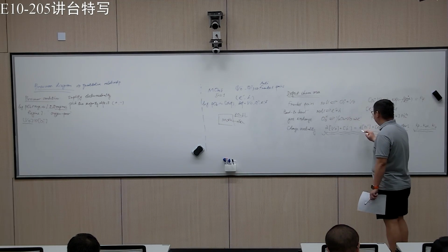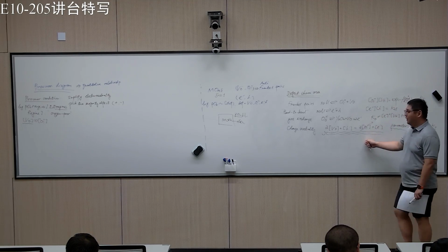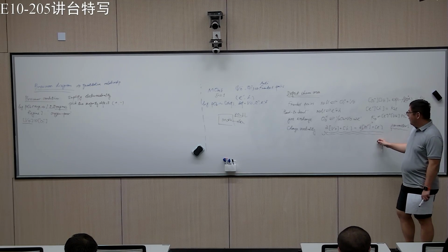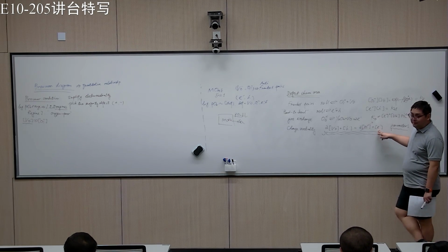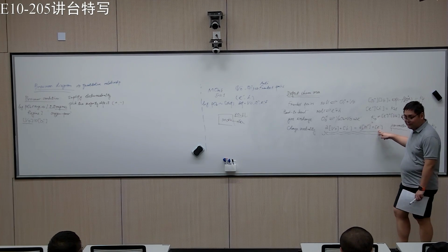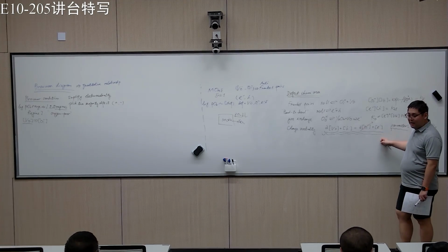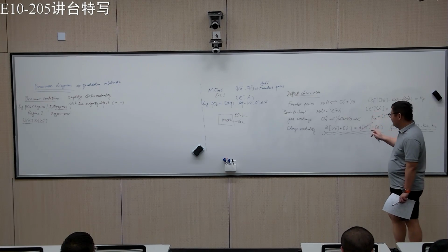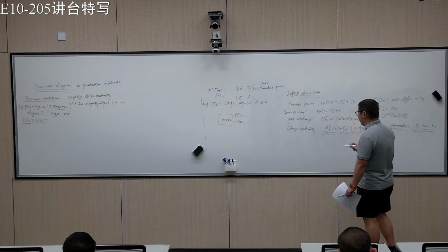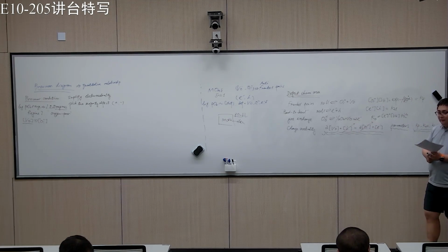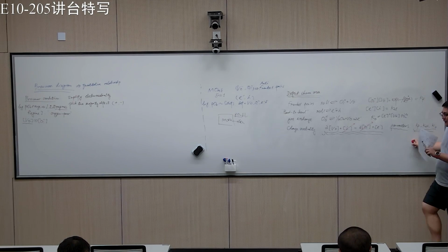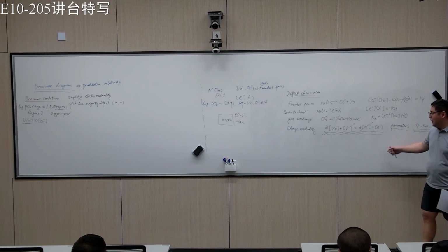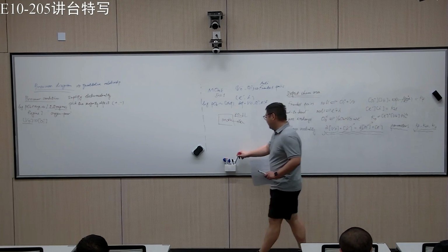The first thing is that you don't have this anymore; you only have this one, right? Now you have many electrons, because electron and hole numbers are fixed by this relation, so you can also neglect this one. This is the way to simplify the problem, because you take two out and have just one equation here.